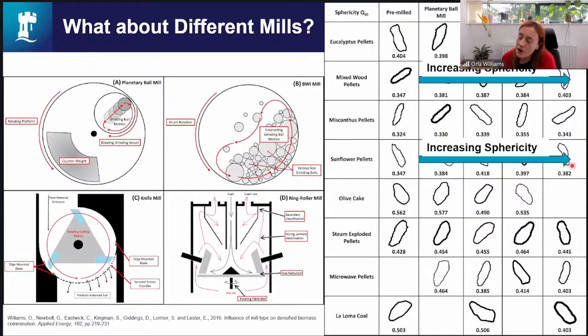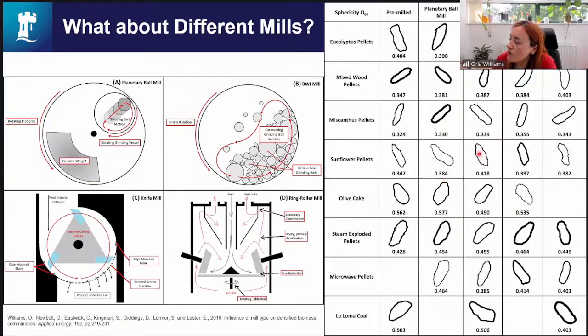So we can see that the average roundness of these particles is increasing when it goes through mills where it starts to choke. We could see that even more for the sunflower pellets, and I'll just go back. You can actually physically see it with these particle images. These are typical images for that sphericity that were taken with the Camsizer. So we can physically measure that increase in roundness that happens during these milling processes.